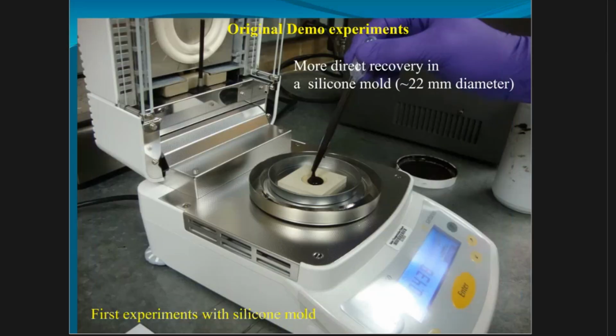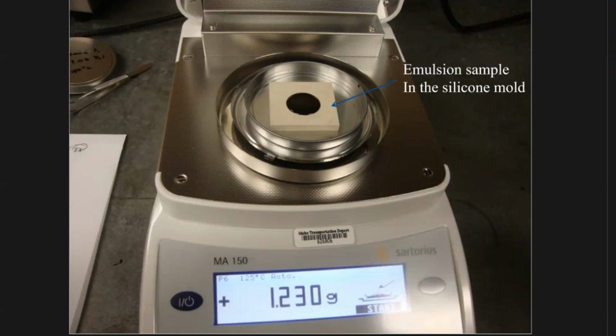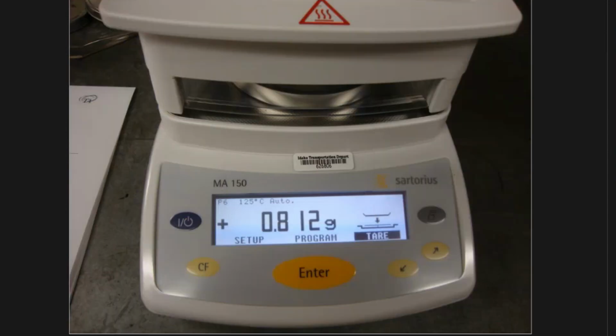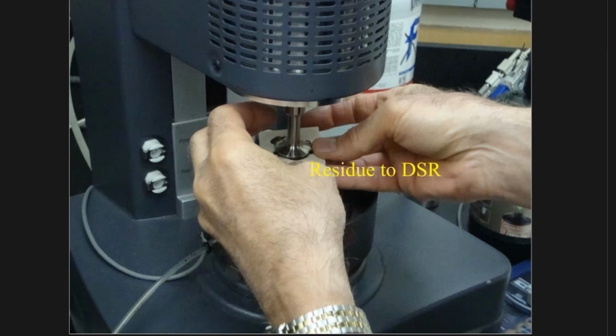And here is where you go through the steps. You can see the weight. Now, emulsion sample, your silicone mold for the DSR. Anyway, that's what you've recovered, enough to put in the DSR, residue DSR. This is not a standard. This would be something that we would do in practice. This is what we're doing in a procedure.